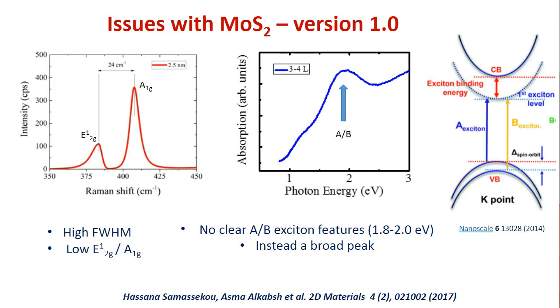So as I said, we did observe X-ray diffraction peaks, but the X-ray diffraction peaks were broad. They were not as sharp as they can be. I'm not showing the X-ray diffraction peak here. On the left-hand side, I'm showing the Raman data, which is characteristic of MoS2. We see two Raman modes here, called the E mode and the A mode. These peaks, again, are known for MoS2, so we found that. But their peaks were broad compared to the single crystal exfoliated sample data.